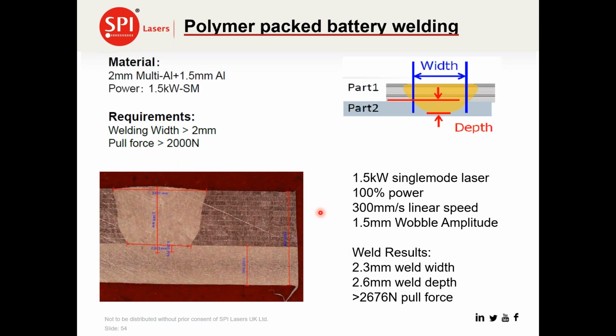And again, stack, we've come across some applications where this is a bit different to the foiled stacks that we're talking about previously, where some of these materials are a lot thicker. And this is an aluminium example where we've looked at a multi-layer stack. The key to the success of this application is making sure that there is no air gap and these materials are absolutely pressed tight together. If that's the case, they can be readily welded reliably and repeatably using oscillation welding techniques. And again, we can get this very square weld with good interfacial area and high strength.